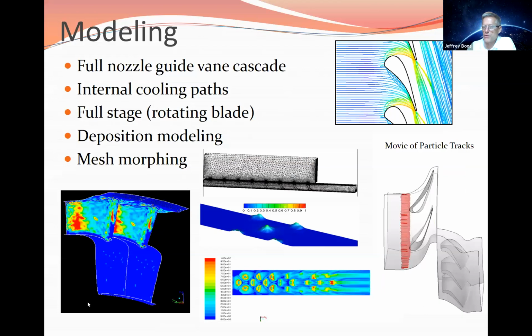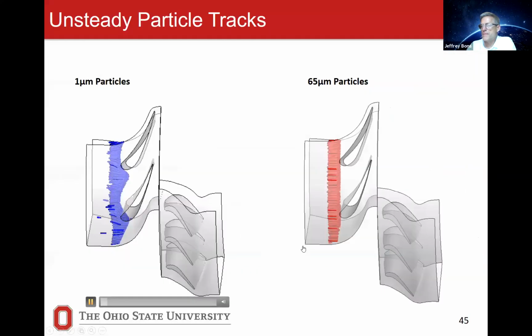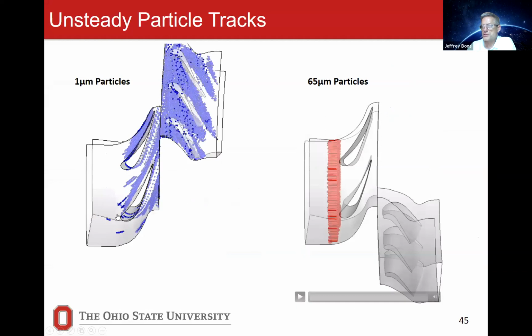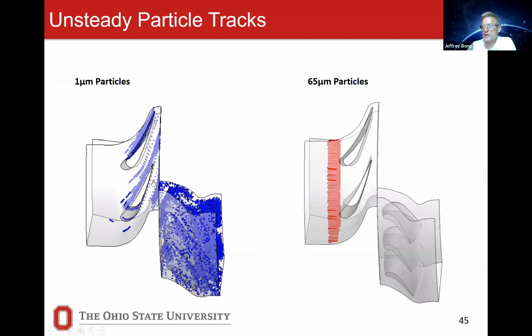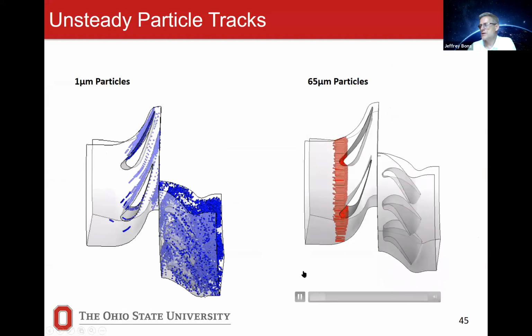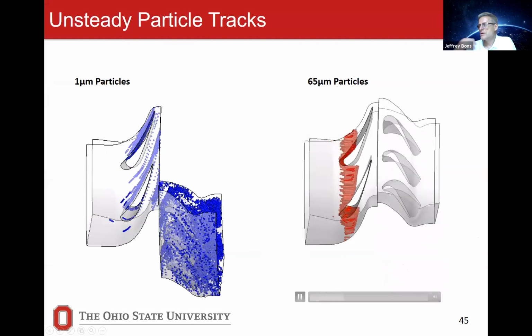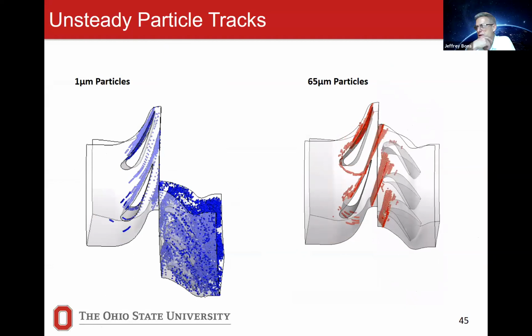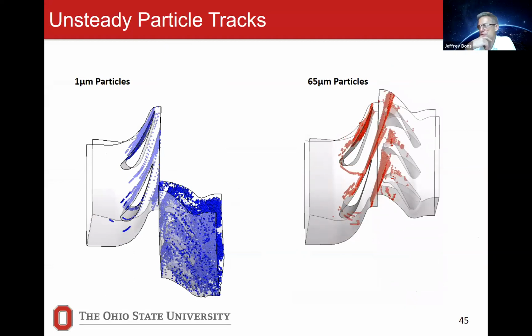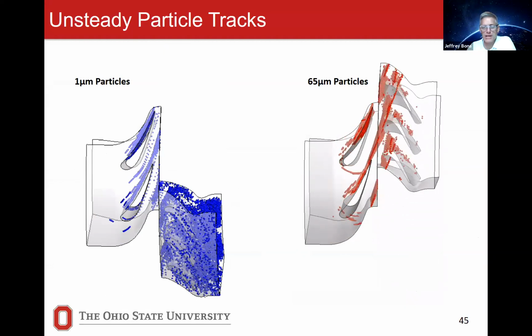This is one where we're actually monitoring particles as they move through a time-accurate solution. So this is the rotor moving relative to the stator. And you can see these small particles kind of follow that flow. If you put large particles in that same flow field, you notice now that they're very ballistic, right? So they're sort of bouncing off the surface and coming back. And that means they have a different trajectory, and they also hit the surface differently. And they may be more or less molten depending on the size as well.